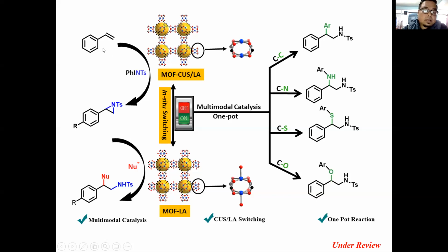So when we couple these two reactions, we can actually create a switching between these two forms, activated and unactivated. Once we turn on the unactivated one, we get this product, and when we turn on the activated one, then we get the aziridine product. In this way, by using simple functional modifications, we could form compounds containing CC, CN, CS, and CO bonds, which is again of high use.